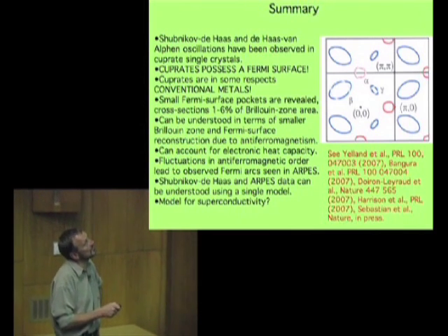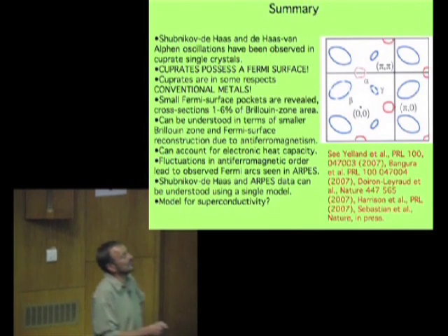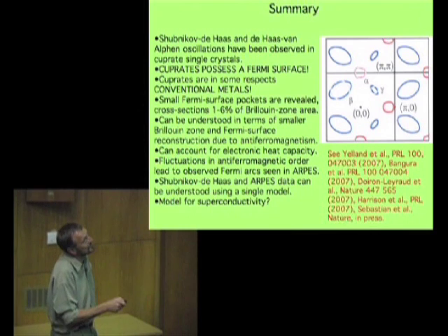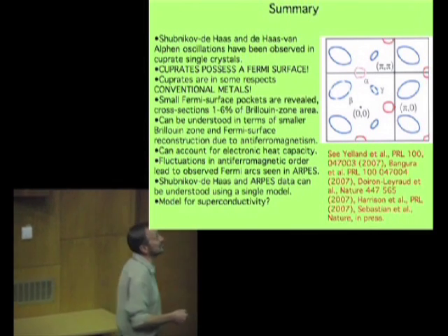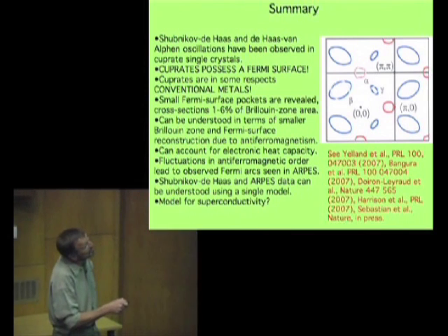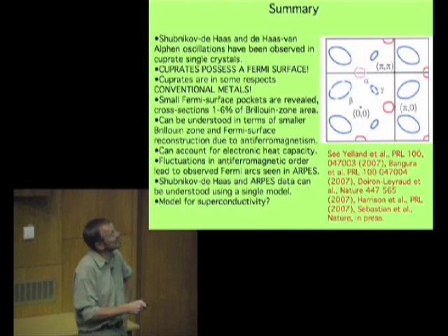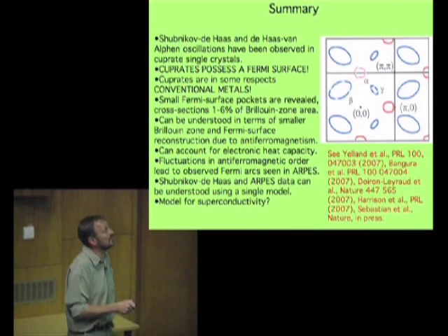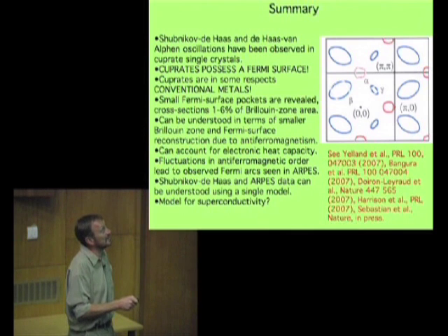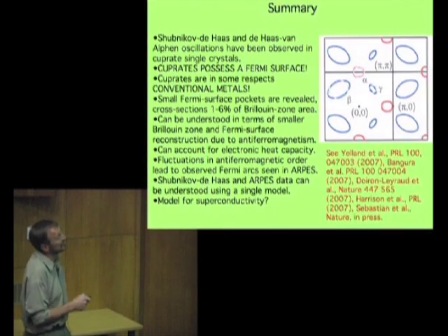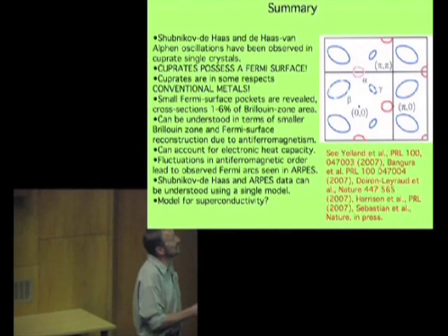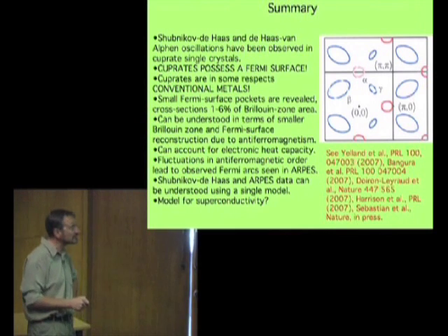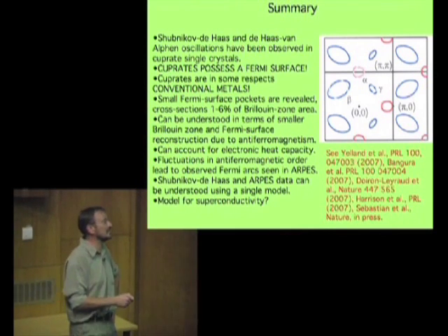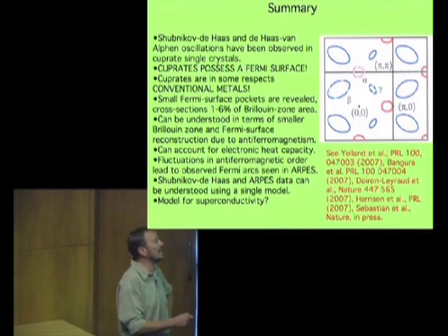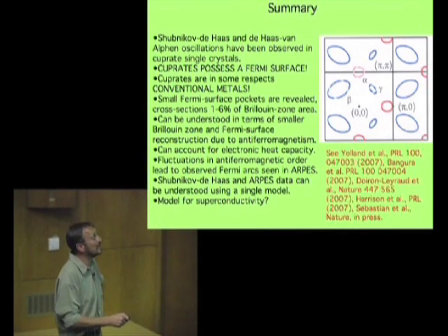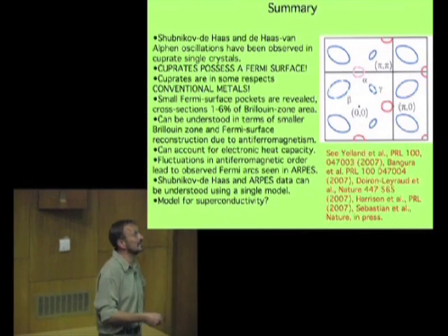This can be understood in terms of a Fermi surface reconstruction due to antiferromagnetism, which breaks the original big Fermi surface up into these little pockets due to the new periodicity introduced into the system. By counting these pockets and their effective masses, we can account for the electronic heat capacity. We can also account for the ARPES data by looking at the effect that the antiferromagnetic fluctuations have on the sizes and shapes of these things. So we can understand the Shubnikov-de Haas oscillations and the ARPES data using a single model. And because the antiferromagnetic fluctuations are so closely related to the Cooper pair wave function topology, we have the beginnings of a model for superconductivity in the high temperature cuprates.